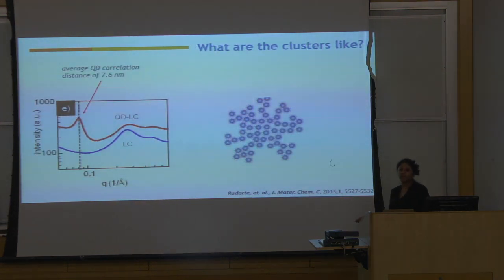Then we look at the clusters, like what do the clusters look like? If after all of this, what we've created is this giant pile of quantum dots with absolutely no order, then it's no good. We kind of ended up worse than we started. We did some small angle X-ray scattering. What we are looking at here is just the liquid crystal with no quantum dots. This is quantum dots in liquid crystal, and we see a very nice peak here. We convert that to distance, and we find the distance on average is 7.6 nanometers, which matches exactly the center-to-center distance when the quantum dots are closely packed together. Also, interestingly, the width tells us that there isn't a huge spread of this distance. It's not like we have some of them 100 nanometers apart and some 7. They're all close by.